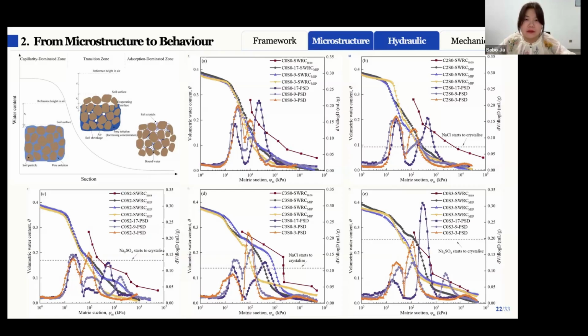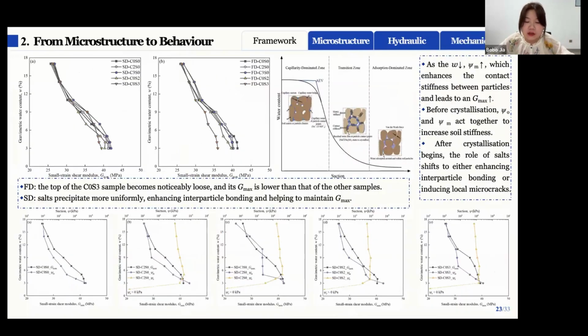And now we can analyze the mechanical behavior, because before going to results, we have to know that the samples are prepared under very similar conditions. So we can mainly focus on the effects of suction and salt. And if we look at the evolution during drying, some trends can be found. Firstly, as water content decreases, matric suction increases, which strengthens particle contacts and leads to an overall increase in Gmax. And before crystallization, osmotic suction and matric suction can work together to enhance the soil stiffness.